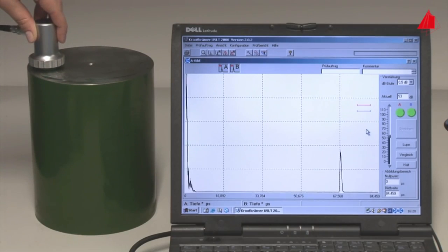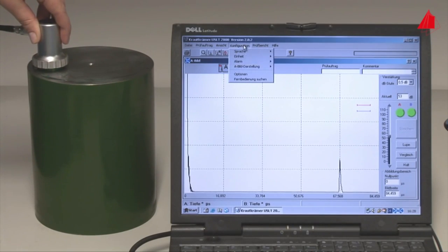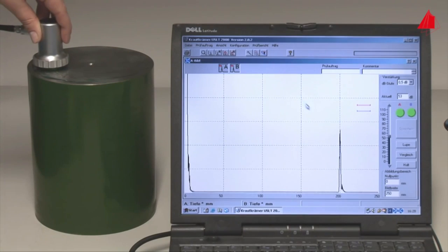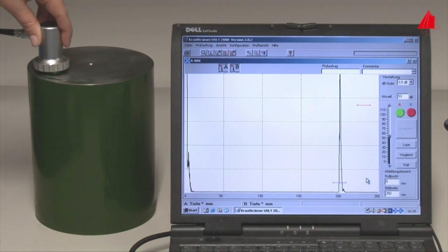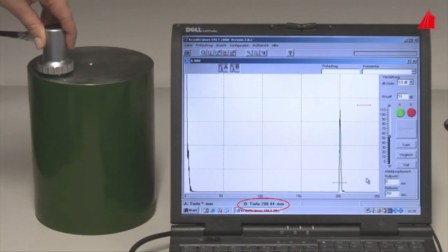Using the velocity of sound in the material, one can plot the calculated depth on the monitor to the right instead of time. A very useful feature. With the help of so-called trigger gates, which may be set on the echoes with a computer mouse, the depth of the defects can easily be read off at the lower left-hand corner of the monitor. The cylinder back wall lies in a depth of about 200 mm below the probe, so the cylinder has a height of 200 mm.